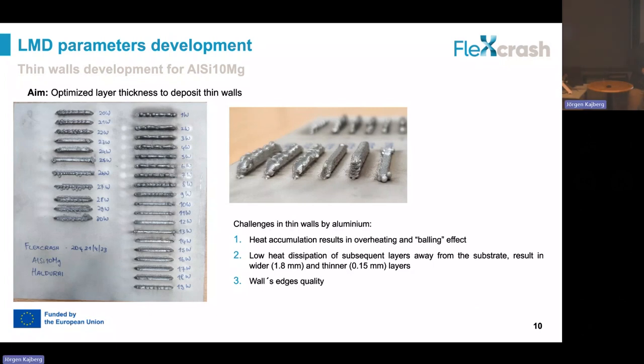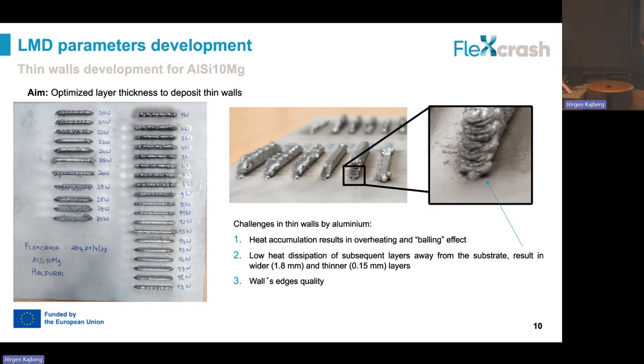As I said before, working with aluminum is quite challenging because when we deposit single tracks, everything looks fine and we have nice depositions. But when we try to build some higher walls, aluminum has a very high tendency of overheating. And this creates, as you can see, balling effects where the molten metal solidifies in this type of balling along the deposition of the track. Also, due to the heat accumulation, you can imagine that the melt pool takes a longer time to solidify. So the molten metal has more time to spread, ending up in a wider and thinner layer every time we deposit.